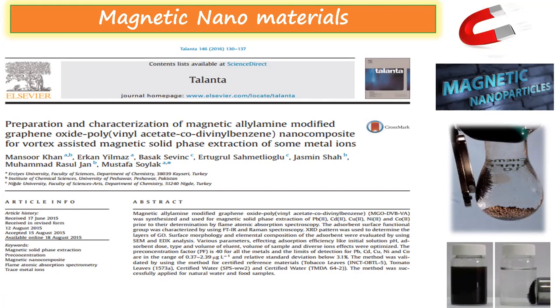This is a very good property for us for the separation of our adsorbents from the aqueous samples. And we also applied to this procedure our new adsorbent, which is a hybrid material, a combination of magnetic allylamine modified graphene oxide, polyvinyl acetate, co-divinylbenzene composites, which is a new procedure called